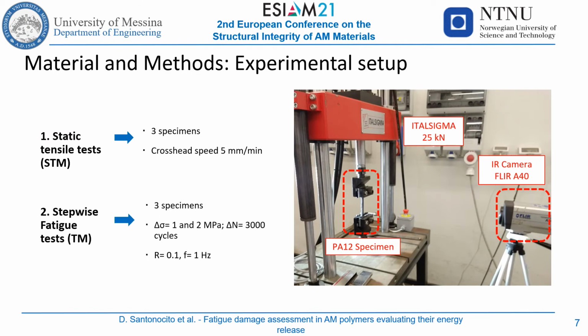Two kinds of tests were performed adopting a servohydraulic test machine. Static tensile tests on 3 specimens adopting a crosshead speed of 5 mm per minute. Stepwise fatigue test applying the thermographic method on 3 specimens with stress level increase of 1 and 2 MPa, 3000 cycles per block, a stress ratio of 0.1 and test frequency of 1 Hz. During static and stepwise tests, the specimen's temperature was monitored with an infrared camera with a sample rate of 1 image per second.